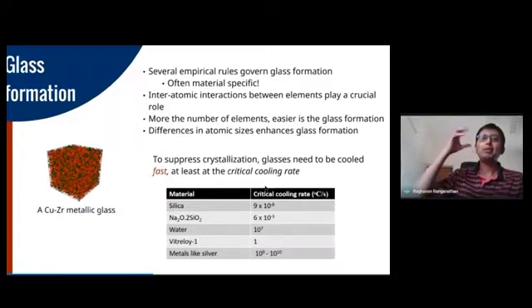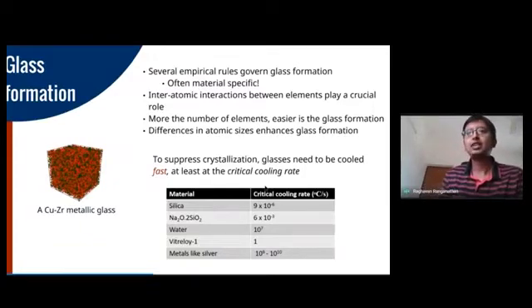You can basically melt silica, take it to its molten state, and then leave it in air, right? And it's very difficult to form a crystal out of it, and it will easily form a glass, a silica glass. Whereas if you go down the scale, water, right? Water, as we know, if you can cool water at this exceptionally high cooling rate of 10 power 7 degrees Celsius per second, then it's possible to form a glass out of it. Any lesser, it will form what's called a crystal, a hexagonal crystal water, crystal ice.